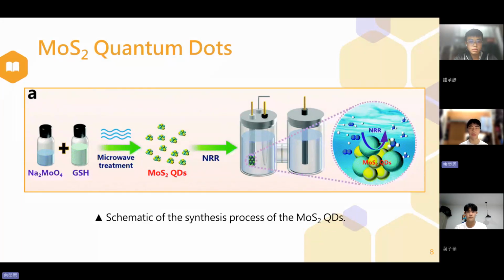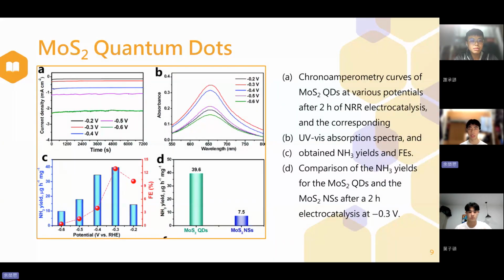The quantum dots were synthesized via a hydrothermal method, resulting in a uniform structure with an average diameter of around 2.5 nanometers. Compared to bulk MoS2 or even nanosheets, the quantum dots had a much higher surface to volume ratio, with significantly enhanced catalytic performance. In their electrochemical test, MoS2 quantum dots achieved an ammonia yield rate of 39.6 micrograms per hour per milligram and a Faradaic efficiency of 12.9% at minus 0.3 V vs. RHE. These values not only surpass those of MoS2 nanosheets, but also compare well with many other reported NRR catalysts.